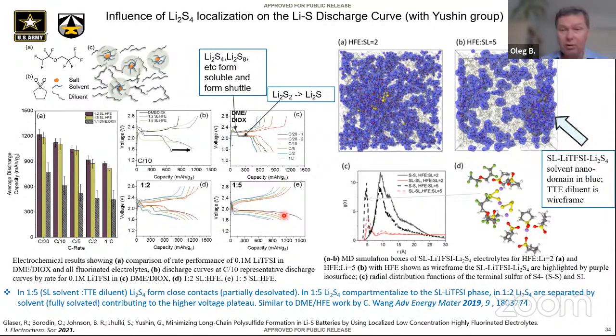So I performed MD simulations of these 2 systems: highly fluorinated ether to sulfolane, that's little diluent, and a lot of highly fluorinated ether with sulfolane. What I'm showing in blue here is the sulfolane and lithium TFSI domain, and I also put in Li2S4, this type of longer polysulfide, which is typically known to be in the shuttle. What we do observe is that there is some aggregation of sulfides in both electrolytes. However, there is a major difference between them.